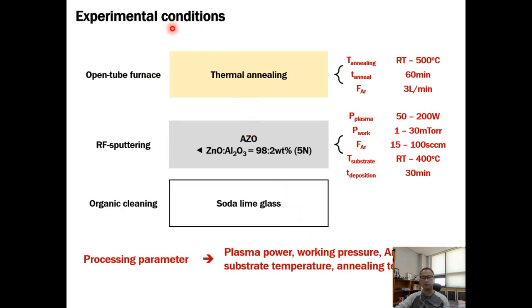Experimental conditions are like this. AZO thin films are fabricated on soda-lime glass substrate by RF sputtering. Sputtering parameters are plasma power, working pressure, argon flow rate, and substrate temperature. The fabricated AZO thin films are thermally annealed under argon ambient in an open tube furnace. Annealing temperature is room temperature to 500 degrees centigrade.